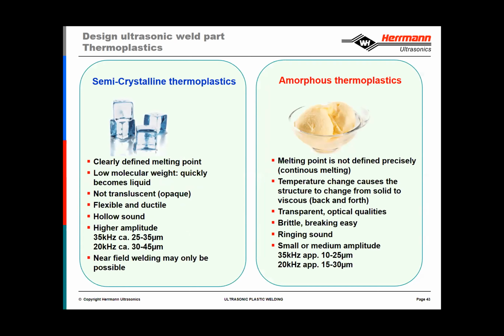So in 35 kilohertz, we're talking about 0 to peak amplitudes in the range of 25 to 35 microns. Or in 20 kilohertz, we're looking at amplitude ranges from 30 to 45 microns. And for semi-crystalline materials, we typically limit them to a near-field weld. And what I mean by that is the distance between where the sonotrode contacts the part and where the driven part contacts the stationary part. This distance should be 4 millimeters or less.